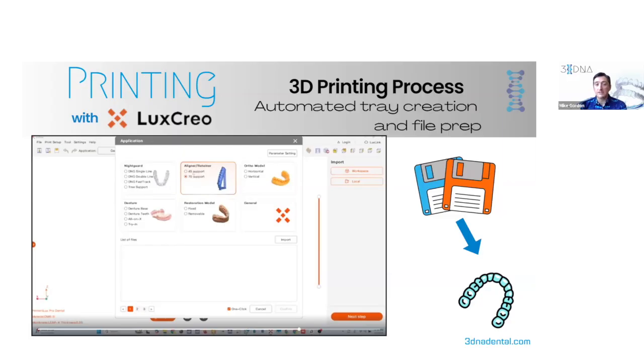But I think the main difference again is just the approachability. First of all, with LuxCreo, this is a tried and true method in terms of the post-processing. So we're really confident, since biocompatibility is a top concern, and we have not had any issues whatsoever with LuxCreo. And the flexibility of this material is much closer to thermoformed aligners, but because of that shape recovery, in the mouth we can provide a low consistent force with LuxCreo's resin, very similar to a thermoformed aligner, without as big of a stress strain curve changing throughout the day when you first apply the tray in the mouth.